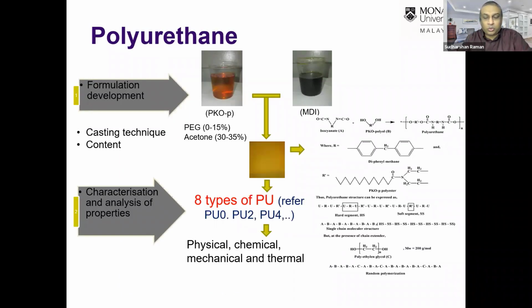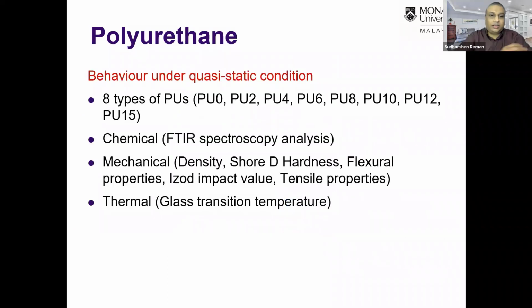So what we did here was we synthesized our own polyurethane by using palm oil as the base material. The plasticizer was varied from 0 to 15%, and we synthesized 8 different types of polyurethane. The designation that we follow here, for example, PU0 represents 0% plasticizer, PU15 represents 15% plasticizer. Okay. And then once we had synthesized the polymer, we tested their properties under quasi-static condition. As I said, there were 8 types of polyurethane that were synthesized from PU0 to PU4, PU6 up to PU15.